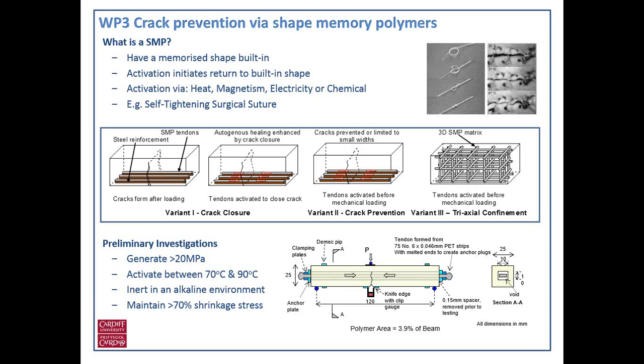And if we can anchor these within a concrete element, we can take advantage of this shrinkage force to then close cracks in concrete and also inflict a compressive stress upon the concrete, which restricts further crack growth. So the idea behind this is to use these shape memory polymers in whichever form we find most optimal, and then put them within a concrete beam to create a 3D pre-stress on the concrete beam. And preliminary investigations for this were very promising.